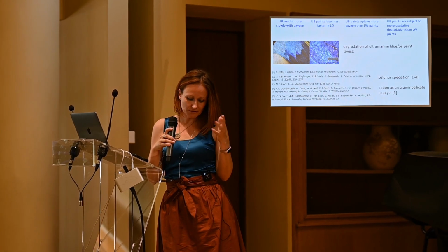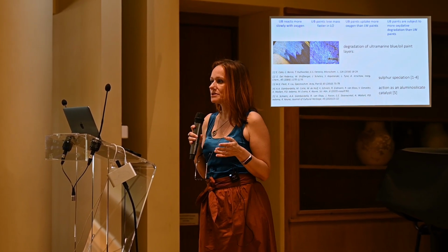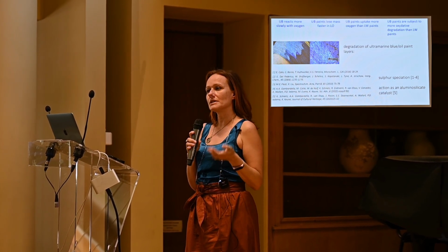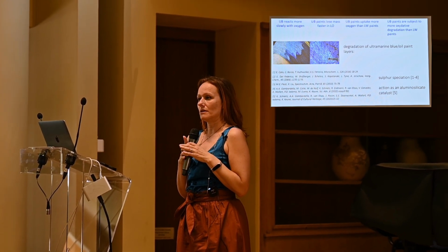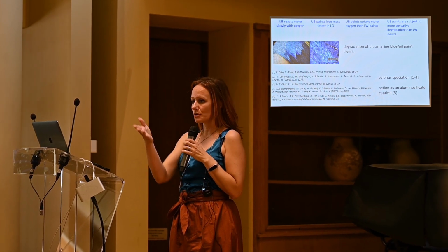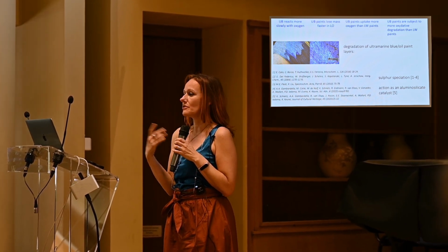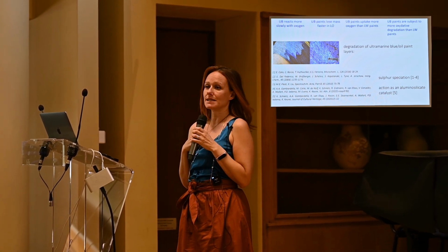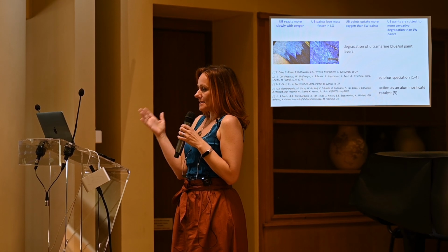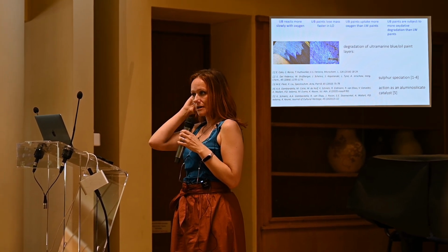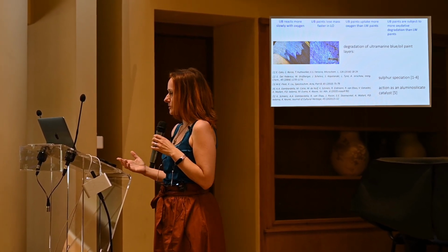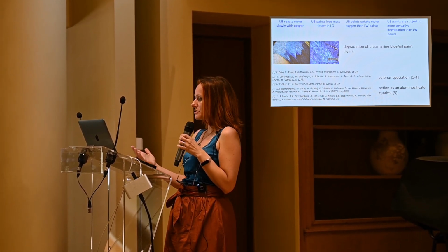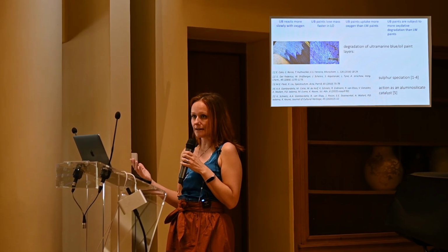Okay, we know that ultramarine blue is peculiar not just for water sensitivity, but there are several degradation issues that are associated with this pigment. We could also see from the presentation before that it is also associated with the formation of oxalates. There are some explanations for this behavior proposed in the literature, due to sulfur speciation in certain cases, or its action as an aluminosilicate catalyst.